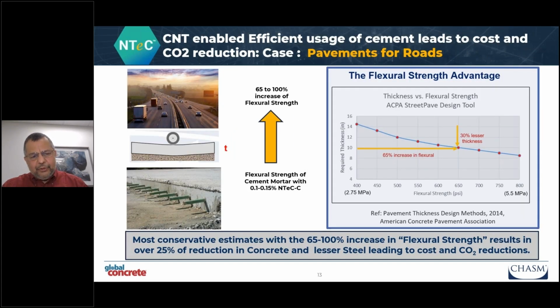A deep dive into the thickness on pavements. This is from the ACPA tool and a calculation done by one of our friends. And so as you increase the flexural strength, even by a moderate 65%, though that's been the minimum we have increased, the thickness can come down by 30% within the code. And this is without including the change of diameters of the bars or the dowel pins in the whole assembly. And this would surely reduce CO2 as well.